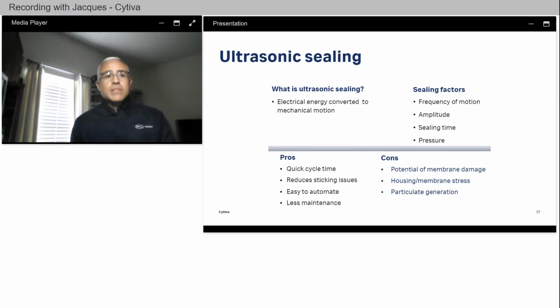Ultrasonic welders are typically available in 20 and 40 kilohertz frequencies. Next is the amplitude, which refers to the length of travel or motion of the tool during the cycle. The distance of travel per cycle is adjustable, and the degree of adjustment depends on the combination of booster horn and input power supply used. As a guideline for devices that are under 1.5 inches in diameter, we suggest a 40 kilohertz power supply. For larger diameters, we recommend a 20 kilohertz power supply. The length of the sealing time, and then the pressure the tool is applying to the seal area.